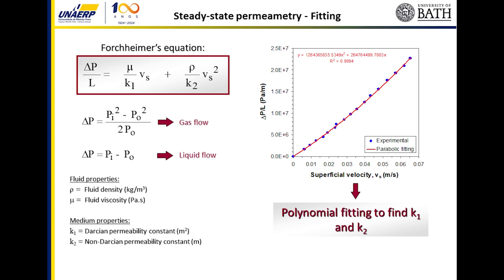This is why I see many people using Darcy's law, because Darcy's law is just a straight line going up. But for a quadratic one, you can have two types of curvatures, and one is wrong. It's very important when you're going to measure. Then you collect the experimental data, do the parabolic fitting, and get the two coefficients. That's important because the coefficients are medium properties. They do not belong to the fluids.